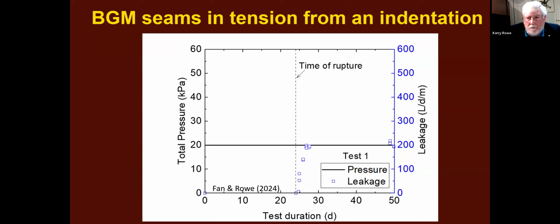And in this case, it sat there. It didn't leak for about 24, 25 days. And then it suddenly started to fail. Within about 2 days, it had gone up from basically zero leakage to 200 litres per day per metre of head. That's for a 600 millimetre long divot. And in fact, the opening up was 500 millimetres long, as you'll see in a moment.